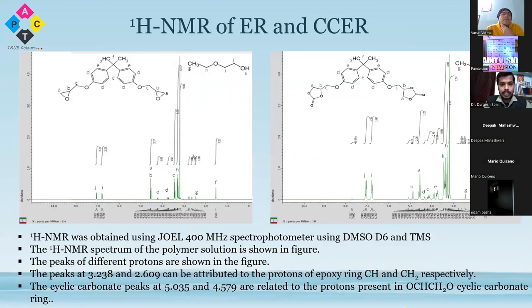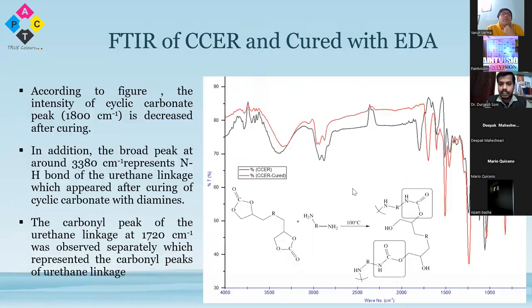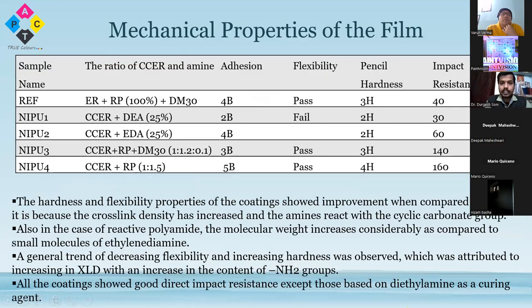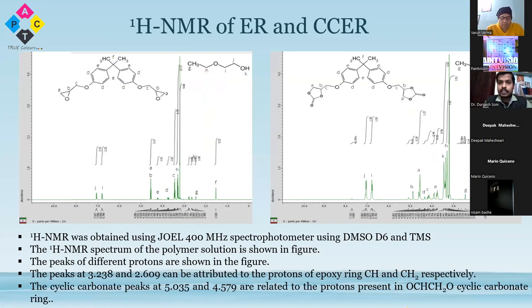And this is the NMR spectrum of the reactant and the product. This is the reactant and this is the product. And correspondingly, the peaks can be seen at 3.238 and 2.609. It is corresponding to the CH and CH2 of the epoxy group. And at 5.035 and 4.579, it is corresponding to the CH and CH2 of the cyclic carbonate group, which also confirmed that the epoxy groups have been converted into the cyclic carbonate groups.